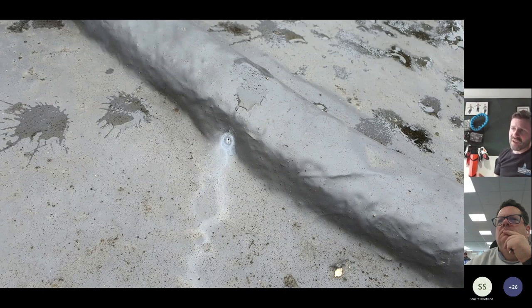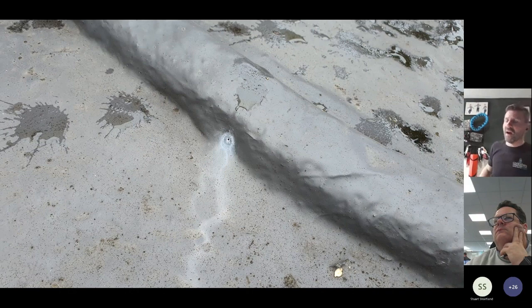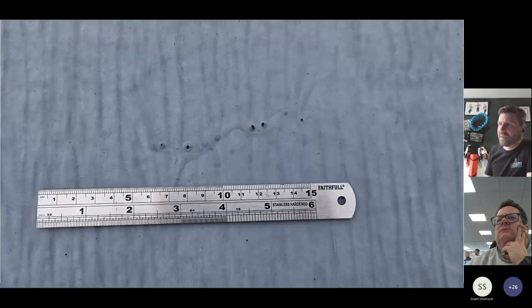If they are left untreated, this is what can happen. Those pinholes will suck water in. That water then will freeze and thaw, expand and contract. Eventually, it will cause a blister or delamination in the coating. Again, you can see another example of some pinholes.